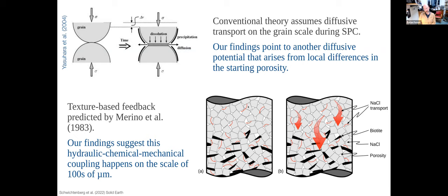So essentially, where the classical theory predicts that salt is just being transported during dissolution precipitation creep around the corner, as I said, there is also a potential for salt to be transported on much larger distances here. And that is sort of destroying or clogging up, as you want, the porosity in that central layer.